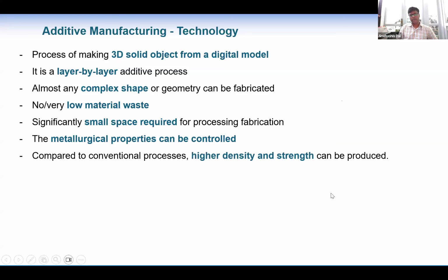Higher density is possible here. In conventional manufacturing, for magnesium, generally by casting you can get about 98% relative density. But in 3D printing, we already get more or less 100% density. Strength is also much higher, like 1.5 times higher. For example, for titanium alloy we can get 1400 megapascal, whereas the casting process gives 900 megapascal ultimate tensile strength. So it is always higher than the conventional manufacturing process.